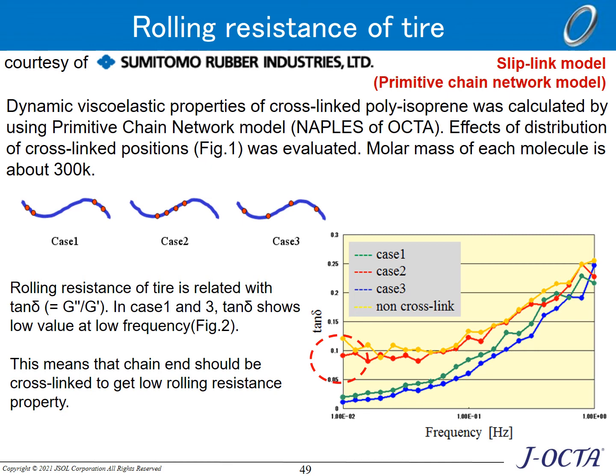Tangent delta, the ratio of G'' and G', was evaluated. This value is related to rolling resistance. A low value is preferable. These results show case 2 is not good because the tangent delta is high. This means cross-linking around the end of the chain is important to reduce the rolling resistance of tires.